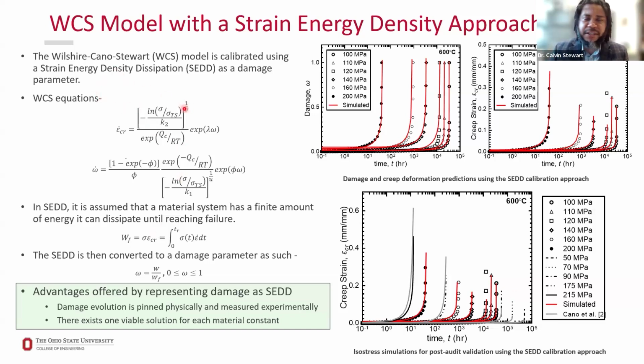Wilshire-Cano-Stewart model. It's a model that integrates the modern Wilshire equations for creep rupture, which are very, very popular, have kind of become the new de facto over Larson-Miller, with continuum damage mechanics, so that we can both predict stress rupture, we can predict minimum rate, but we also can predict the creep deformation and damage evolution within materials, right?